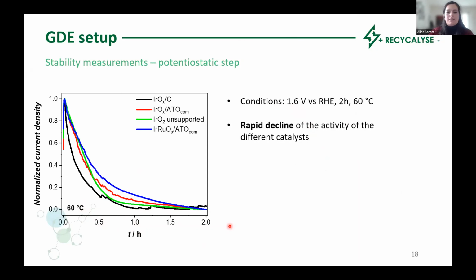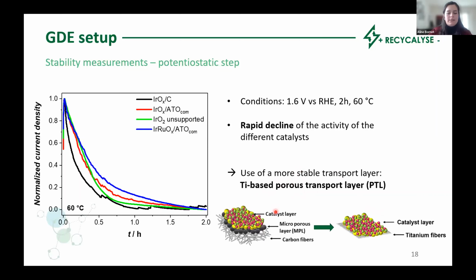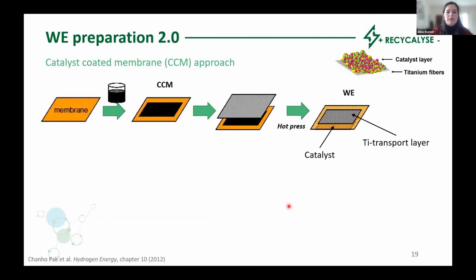And actually, this something else might be the transport layer itself, as it is carbon-based, and it is well known that the latter is not stable under the harsh OER conditions. So to test this hypothesis, we decided to use another transport layer, namely a titanium-based one, that is also called PTL. We use this one as it is commonly used in the PEM electrolyzer. In other words, we want to change this carbon-based part by a titanium-based one.